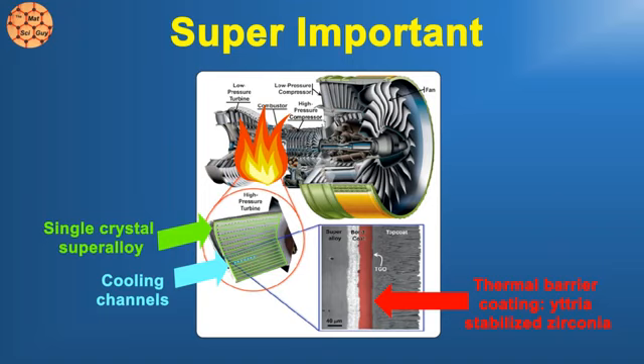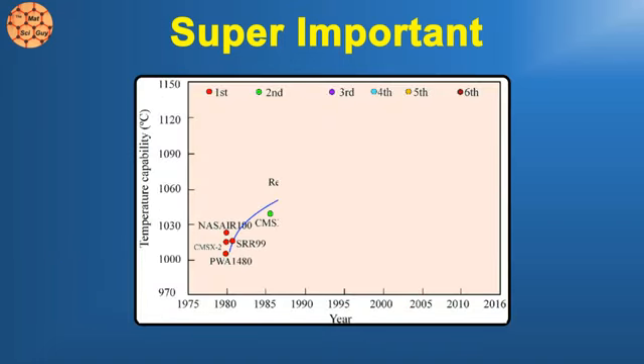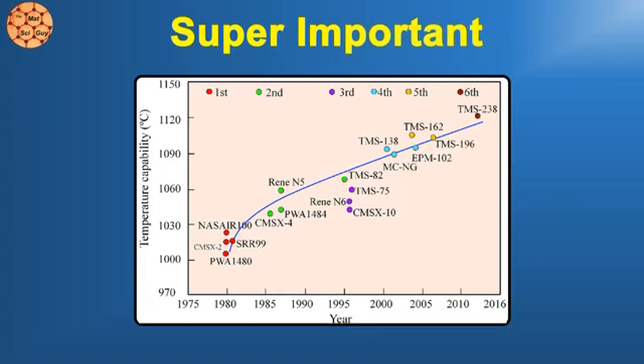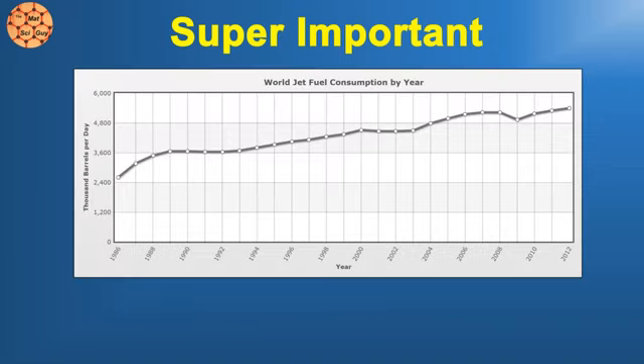The development of superalloys, along with advances in cooling and thermal barrier technologies, has allowed the maximum temperature of jet engines to increase significantly over the last 30 years. The result is that the latest superalloys can withstand prolonged exposure to temperatures in excess of 1100 degrees Celsius. Because of the thermal barrier coating and cooling channels, the actual maximum temperature inside the turbine is even hotter. Considering the amount of jet fuel used every year, it's likely that the development of these materials has saved literally millions of liters of fuel. The economic and environmental impact of the fuel savings is truly staggering.